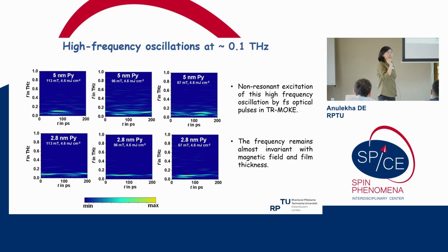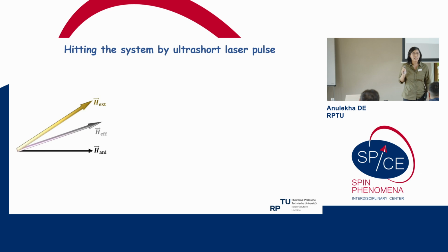So this frequency remains almost invariant with the variation of the sample thickness, the pump fluence, or the magnetic field. And these high frequency oscillations are non-resonantly excited in our case with just an optical pump and optical probe. So we are trying to understand what may be the origin of these high frequency oscillations.